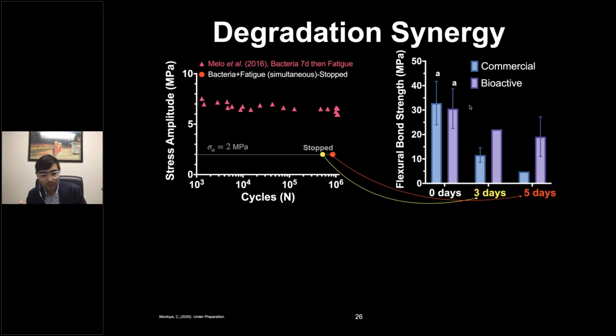So we're using 2 megapascals, which is 3 times less than that. We're putting just a tiny bit of force, and at the same time submerging this composite into this realistic media. We're loading the sample to see the synergy of mechanical degradation and bacteria degradation on the bond strength. We're stopping the test at day 3 and day 5, and after stopping, we break the sample and assess the flexural and bond strength.